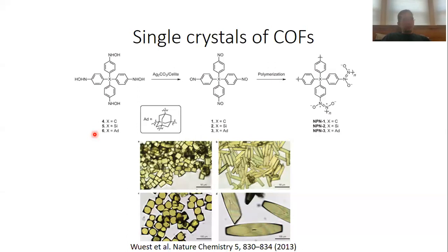Nonetheless, it would be very desirable if you could also produce COFs in single crystalline form, because then one could easily analyze these single crystals by single crystal XRD. In a few cases that has succeeded, in cases in which the covalent bond formed between the building units is particularly labile. All right, and the first example for which that has been demonstrated is actually shown here.